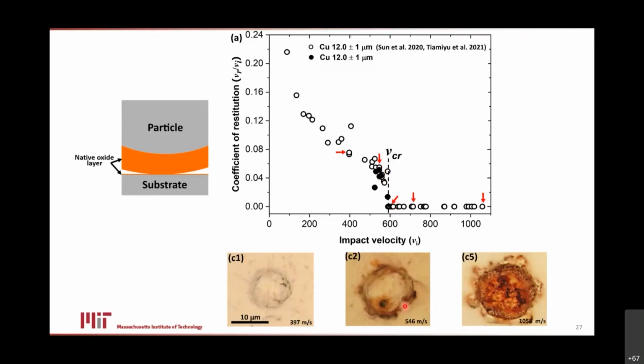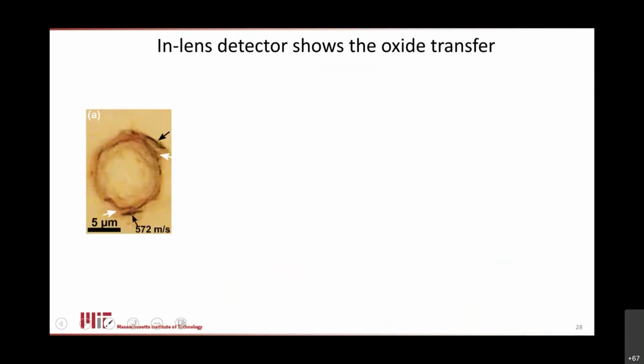But more importantly here, also around the periphery, look at these patches of rust color. You are looking at oxide flakes that have cracked up on the surface of the particle, and they have detached and fallen out. They've delaminated and they've transferred onto the substrate. So the onset of jetting is now also a moment where we see the onset of transferring oxide. So we are indeed cracking up that oxide layer.